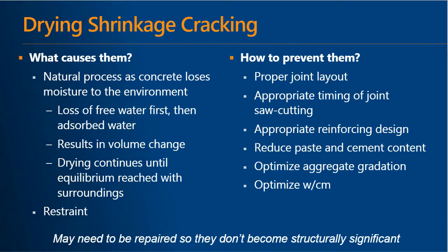In addition to considering the overall drying shrinkage of the concrete element, you also have to think about differential drying within that element. Say you have a bridge deck where the top may dry faster than the middle or even the bottom of the deck, especially if forms are kept in place for some time.